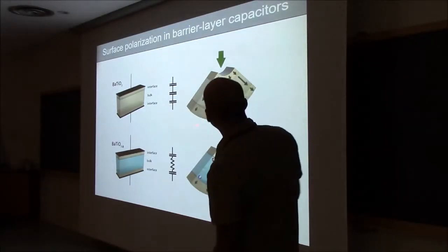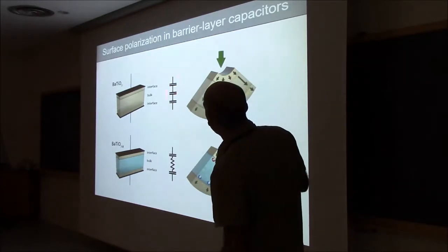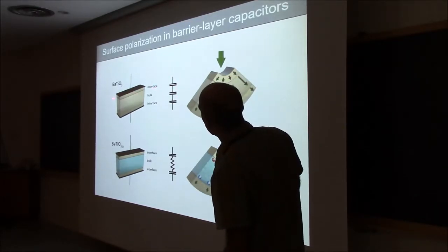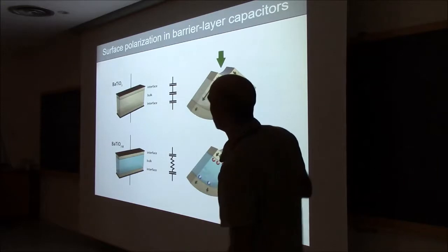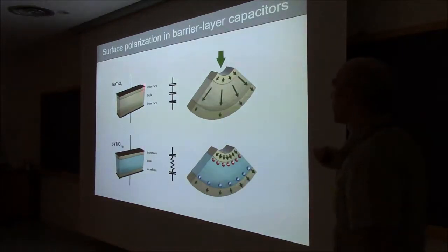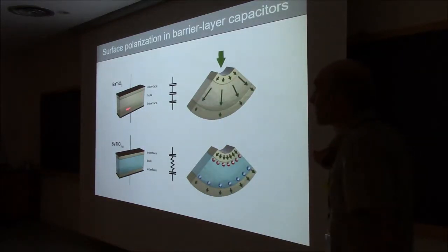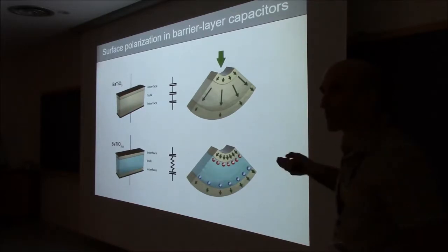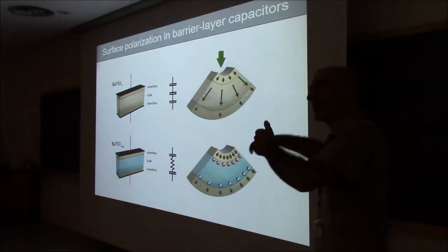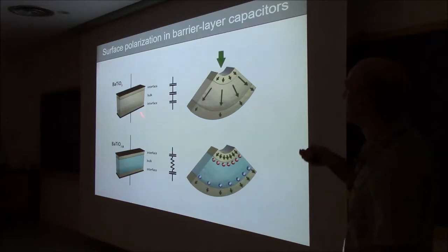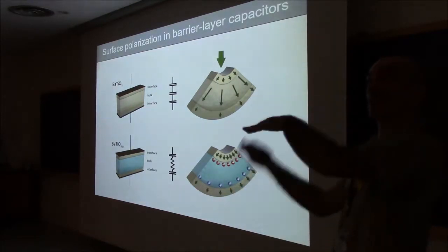So what's happening here is the following. If you take BTO and you try to bend it, basically you can think of BTO as being 3 capacitors in series, the interface being one of the elements, the bulk being the other one, and the other interface being the other one. You can measure the capacitance of this, and mostly the capacitance will be dominated by the bulk. Because it's 1 over the capacitance. It's 3 capacitors in series. The thing with the smallest capacitance, which is the thickest element, dominates.